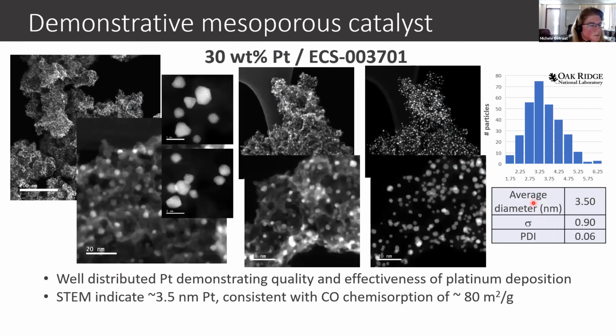With those catalyst supports, what we do is then deposit platinum or platinum alloys onto these materials. And this is an example of some of our 30 weight % platinum that's been deposited on our engineered catalyst support. And you can see extremely good distribution throughout the entire carbon support, and this is done in collaboration with Oak Ridge National Lab. Particle sizes are averaging about 3.5 nanometers, really just demonstrating the quality and effectiveness of the platinum deposition onto these materials.